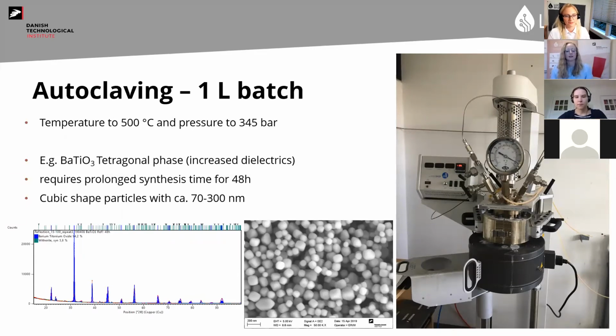So if you want to have a very long synthesis time, but you need to have high temperature and high pressure, we use the autoclave, where for this example, I have taken our material barium titanate that we made. That one needs to have a very certain crystalline phase to have the best dielectric properties. And to do that, we need to have 48 hours in this 500 degrees and 345 bars environment. And that's where we then use the autoclave because the flow synthesis is not capable of doing this. And here at the bottom, you can see the XRD pattern and the STEM picture of the results.